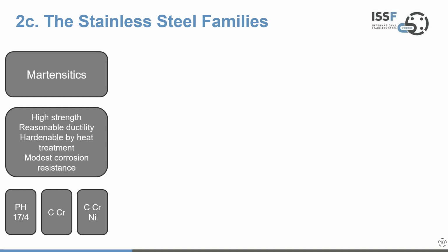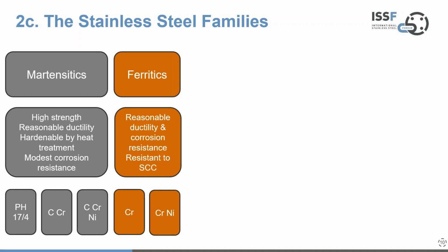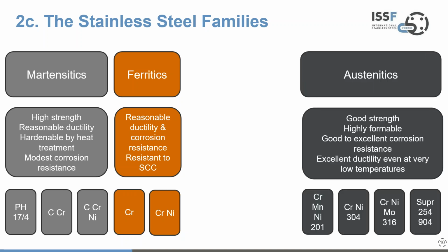Now, moving on from martensitics, we have the ferritic group of stainless steels. Here we have again reasonable ductility, but somewhat better corrosion resistance, and specifically a resistance to a corrosion phenomenon known as stress corrosion cracking. And these are either straight chromium steels or chromium nickel steels. And now, for reasons that will become apparent in a few moments, I'm going to move to the right-hand side of the family tree, so to speak, and talk about the austenitic group of stainless steels.